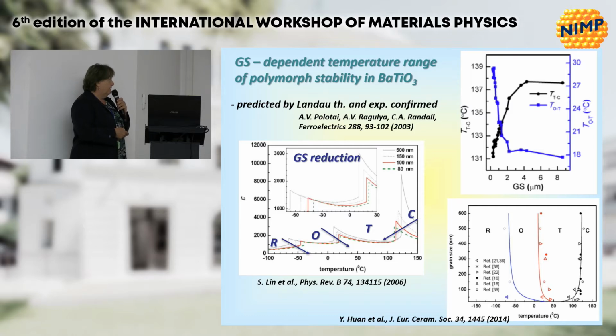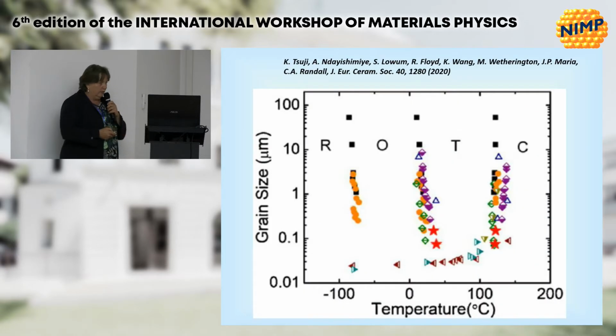These transition temperatures have been shown by multiple experimental data, including quite recent ones, to shift with reducing grain size. The rhombohedral-orthorhombic and orthorhombic-tetragonal transitions move towards higher temperature when we reduce the grain size, while the cubic-tetragonal transformation moves towards lower values. Practically, the extension of the tetragonal state tends to reduce strongly when we decrease the grain size. This effect is predicted also by Landau theory, and as I said before, it was confirmed by many data, including the recent ones from the group at Penn State, shown by these stars, which correspond to very new ceramics prepared by a new method of low temperature sintering.